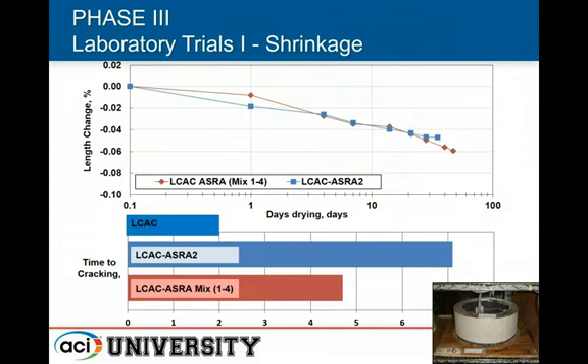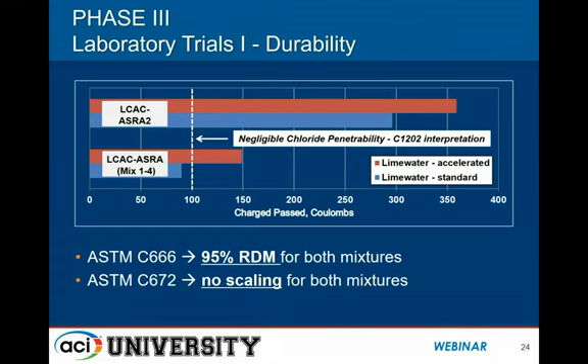What you can see in this figure is that despite the fact that these mixtures had similar linear drying shrinkage, which is the top chart, the bottom chart tells us that they had vastly different cracking behavior. Ultimately we want to address this further, because all of the mixtures we looked at were cracking within the first week. So we weren't really satisfied with this behavior. We want to get that cracking time frame out past 1 week before we start to use this material in the field.